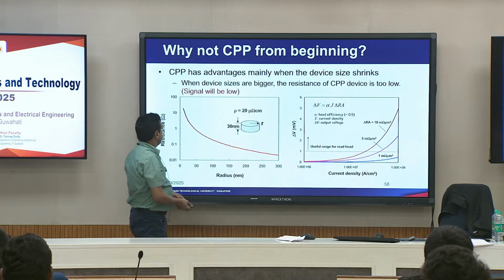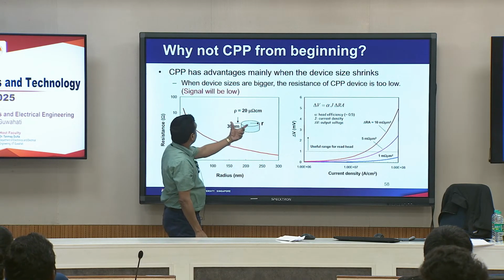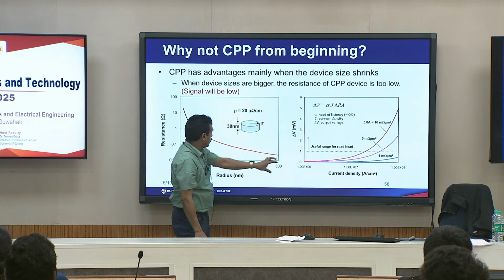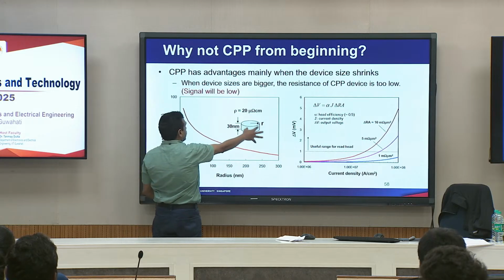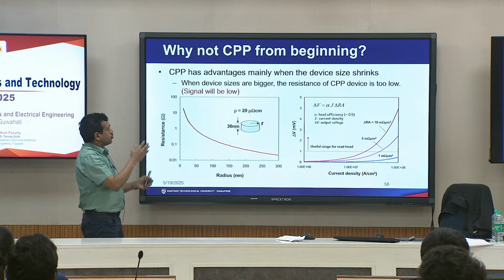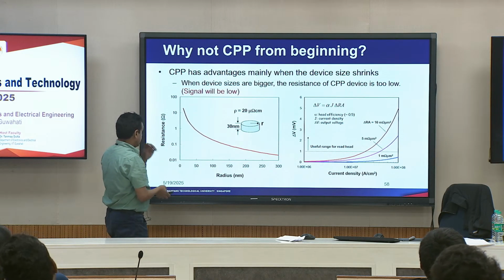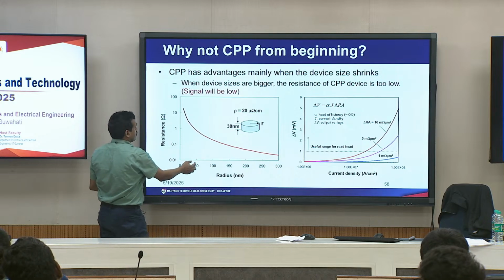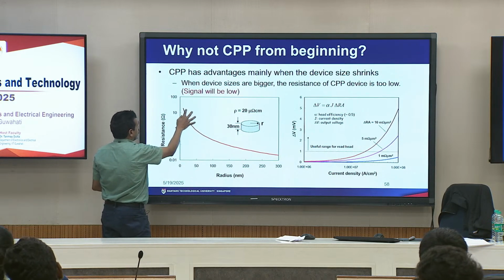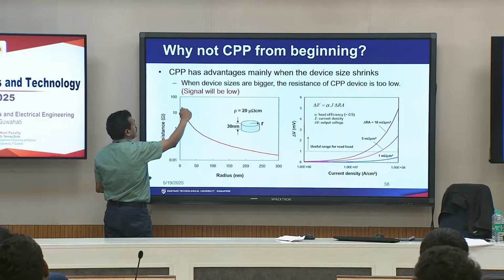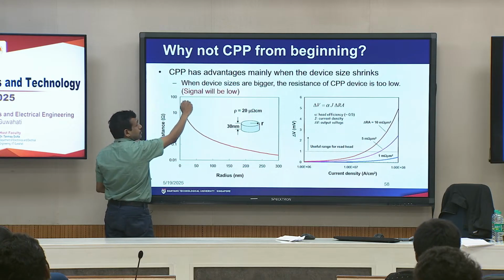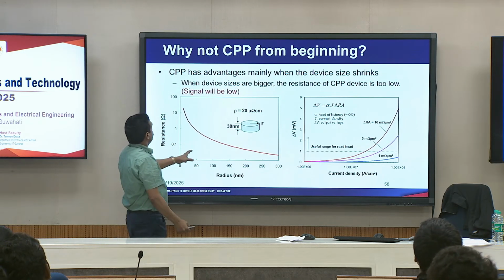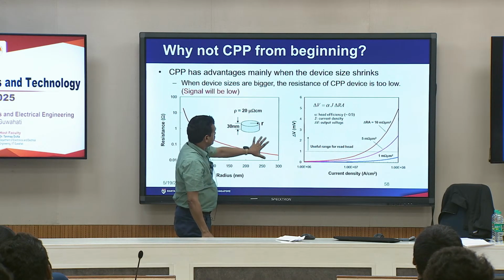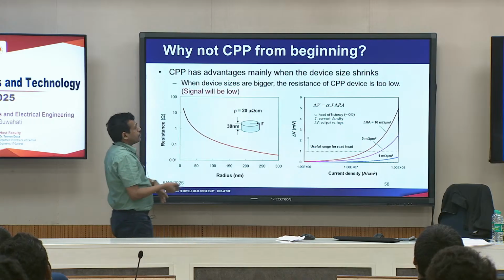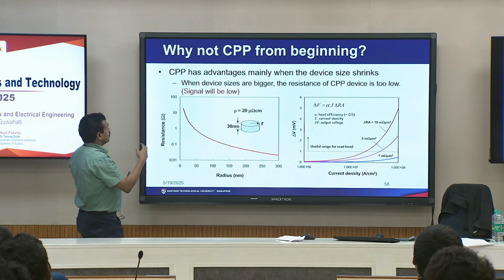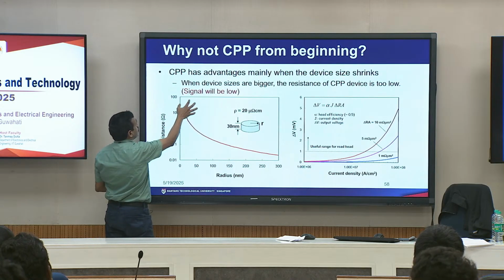When the diameter of the GMR device is around 300 nanometer, for example, the resistance of this whole device is so low that the high resistance and low resistance will be too small to detect. On the other hand, when you go down to smaller sizes, say 50 nanometer, your resistance is around 10 ohms. So the swing between the high and low resistance will be reasonable enough to detect. For very large device sizes, this configuration is not good. That is why people use current in plane, but once we go towards high density smaller devices, CPP becomes useful.